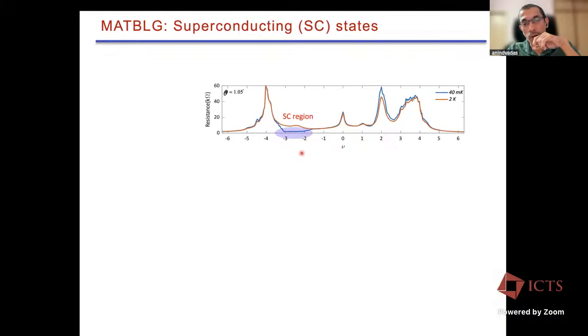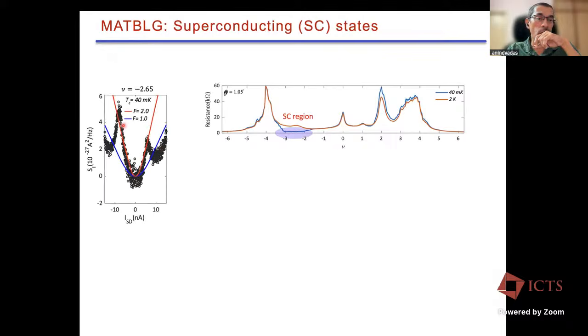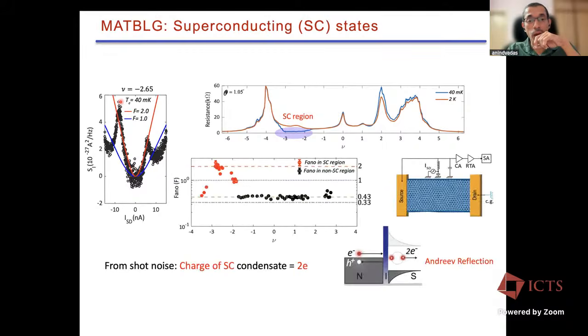And once you start doing this, interestingly, what we see is that the Fano is much larger than 0.43, and it turns out that in this case the data can be qualitatively nicely described as Fano factor 2. And if you look throughout this superconducting dome, this is the Fano analysis around the regime, the Fano 2 around the strongest superconductivity regime, and it drops down as you go closer to the Fermi liquid regime.